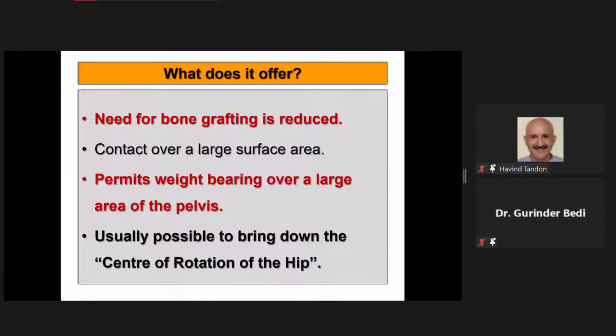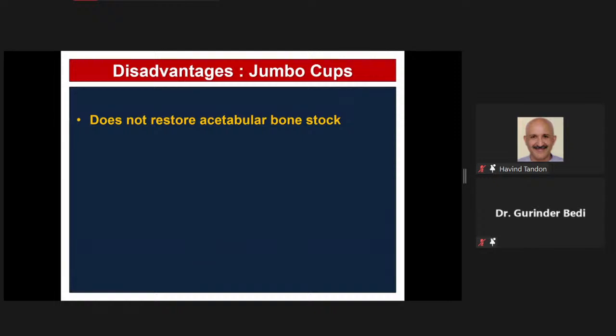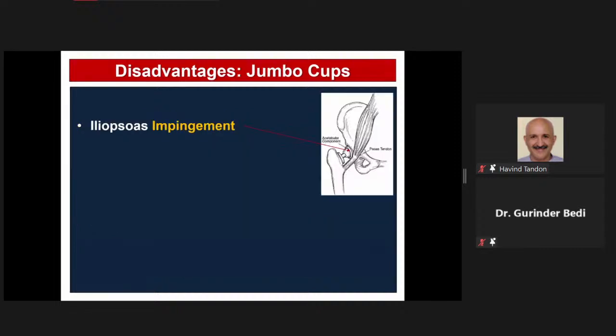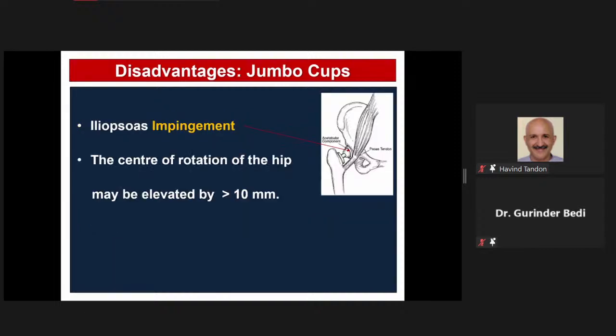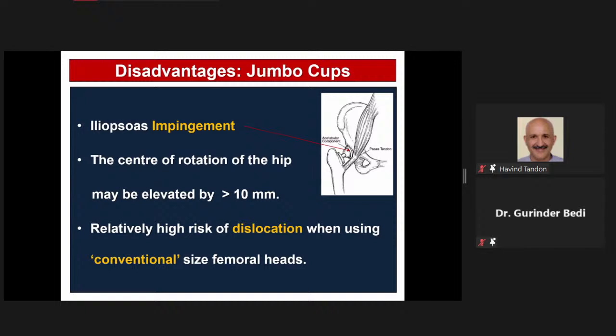So what does a jumbo cup offer? It permits weight bearing over a large area of the pelvis because of good contact over a large surface area. The need for bone grafting is obviated, but at the same time, it does not restore acetabular bone stock, which is quite important for younger patients. You can sometimes even remove more bone while reaming. They can have impingement of the iliopsoas because of bigger size, and the chances of dislocation are slightly higher with these cups when you use a conventional sized femoral head.